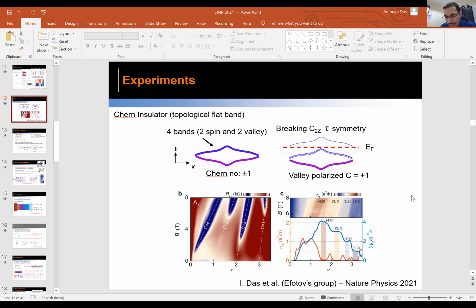In your sample, with boron nitride, you symmetrically put the gate potential to change the densities? Yes, we have a gate potential, but in our sample, I don't know whether we are breaking this C2z. It's not the displacement field. I think they do it by aligning to this boron nitride structure. Because you have boron and nitrogen, because of that you basically break this C2z symmetry.